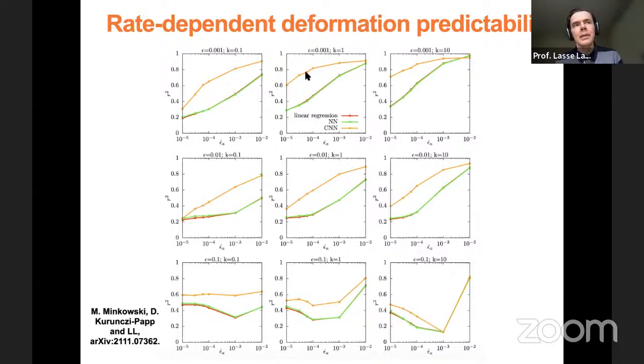So it seems that the CNN is able to extract some features from the initial configuration that we could not think of, which is kind of interesting. I'm not sure what exactly this information is that the CNN is able to extract from the initial configuration, but there's something, because with the same data set, it's able to do better. But anyway, the key point here is that for all of these models, there's a clear rate dependence of this effect, especially for small strains. So in this top row, you have a monotonic increase of predictability as you increase the rate. So the larger your strain rate, the easier it is to predict the stress-strain curve.